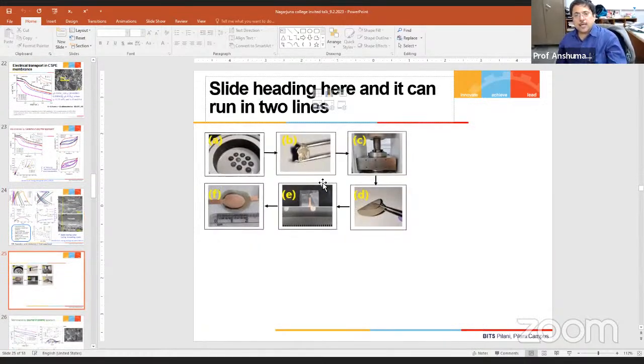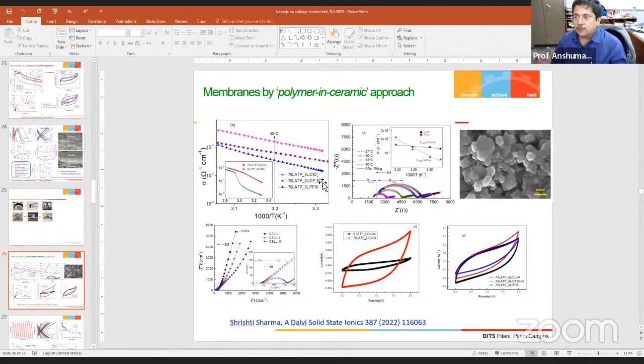All right. Then there was another approach, when we said that when you have a large amount of ceramics, you are reducing the amount of polymer and making a supercapacitor only based on ceramic. Now this is one of the important things, because finally these ceramics are going to be playing a role in batteries and supercapacitors. It's a concept actually, because polymer will also have degradation with higher temperature. So in some way, after some time, you would like to get rid of polymer also. So slowly, if you remove polymer from the matrix of the electrolyte, that means that instead of adding ceramic nanoparticles to the polymer, now you have added polymer to the ceramic.